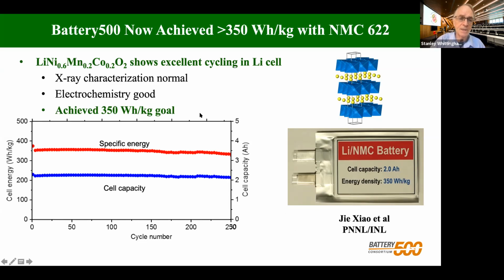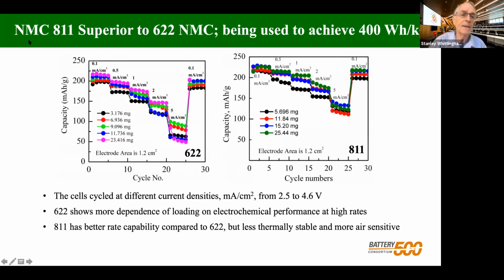So to get the energy density still higher than 350, we need to go to even higher nickel contents. So we looked at what's the impact of changing, say, from 622 to 811, and we found it, in fact, was superior in every way. And don't worry about all the details in this plot. All you need to see is this is different rates. The rate capability falls off much faster for 622 than for 811. And this is done for different loadings of the material from about 6 milligrams per square centimeter to about 25. And the loading has much less effect on the 811 than the 622. So we've, in fact, program has switched over to the 811 material now.